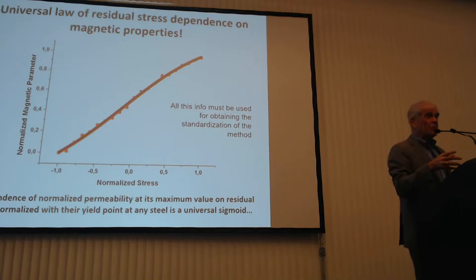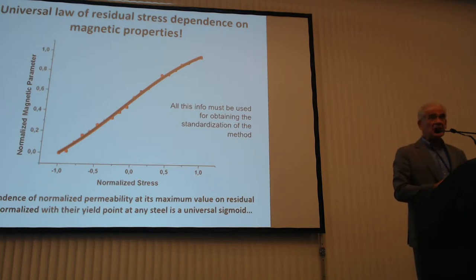This means that if you have an unknown type of steel, the only thing you need to do is to monitor the yield point, the point where the plastic deformation starts. And therefore, you can tell, for an unknown type of steel, the amount of residual stress and the distribution of these residual stresses in the steel, predicting thus the actual time and space where the crack will be.